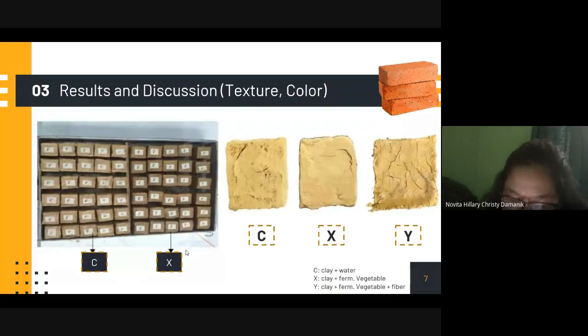So producing the brick samples encountered some difficulties, especially in casting the samples. C and X were difficult to cast due to the extremely clayey properties, different from the Y samples, because there was a natural fiber of sugarcane in the mixture, so that during removal from the mold, it is easier. Some other differences were during the stirring process. Samples containing sugarcane fiber were drier compared to samples that do not contain sugarcane fiber. This was due to the fiber properties of sugarcane that quickly absorb water.